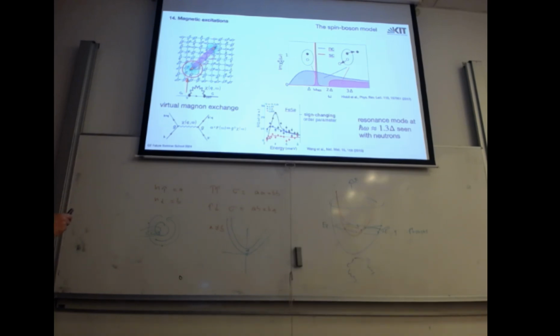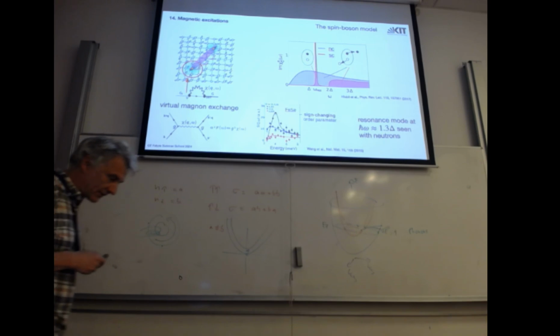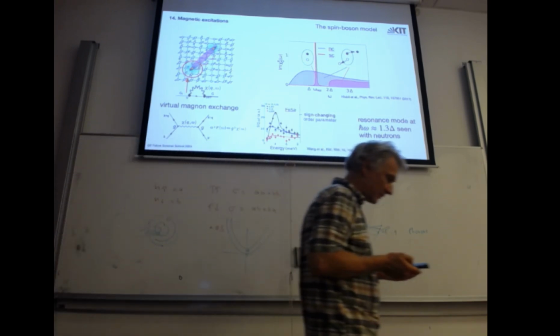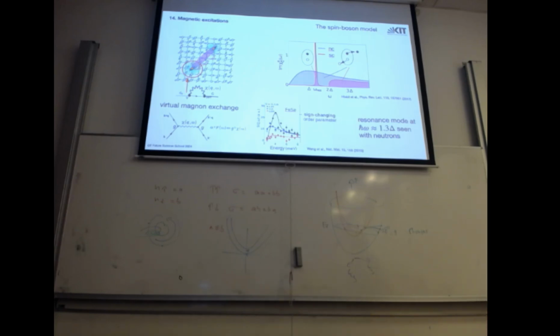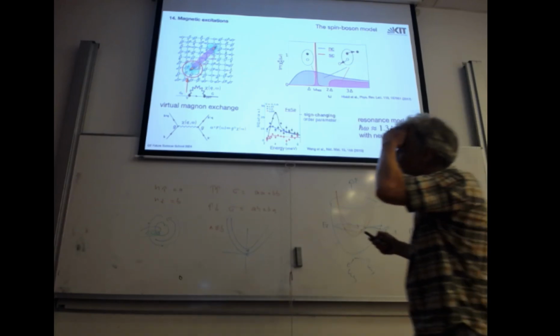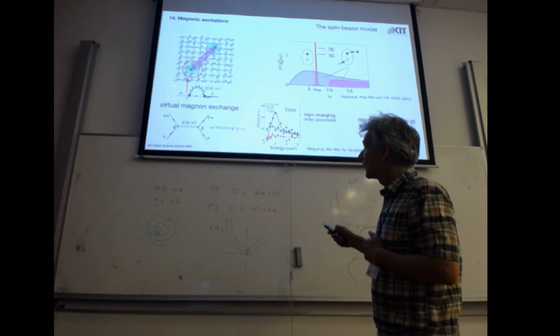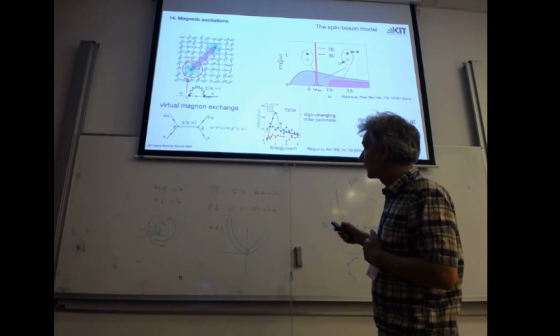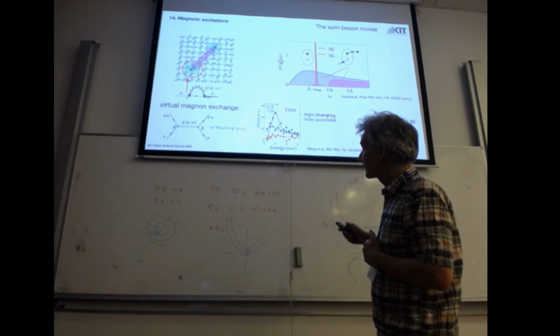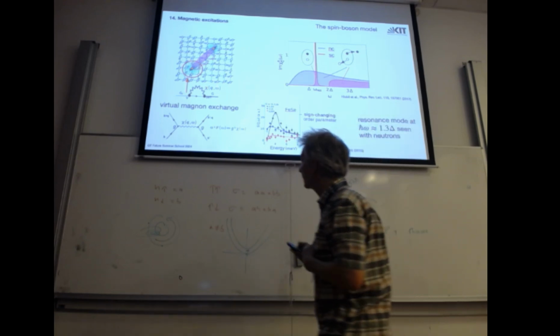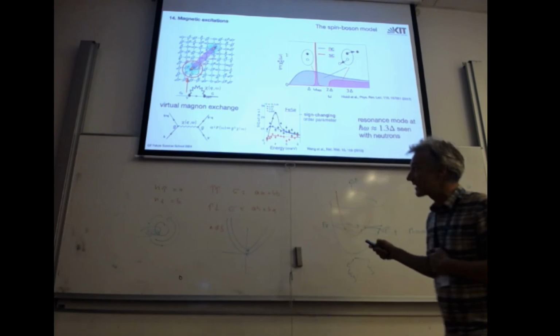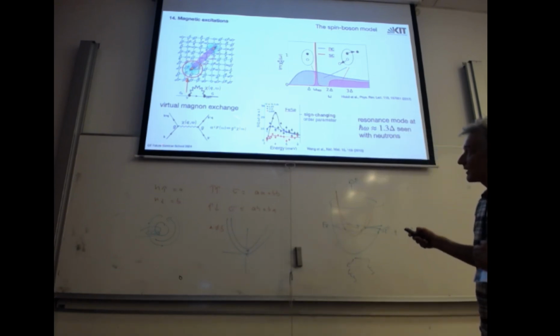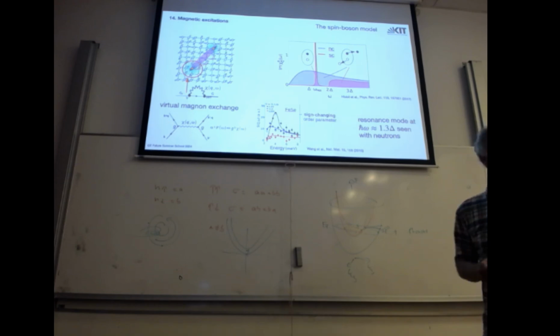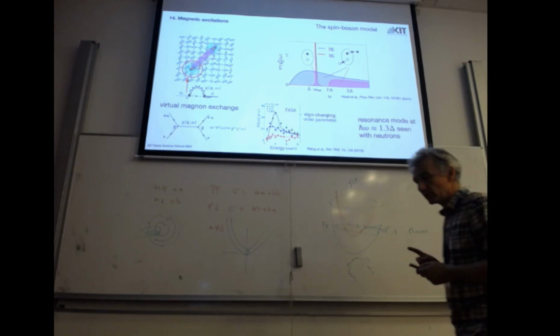And now this screening we have with phonons, so this phonon interaction is now in the spin interaction, and my electron self-interacts via magnon emission and absorption, or with scattering, I can think of two electrons, they exchange a magnon. The difference with the phonon graph.